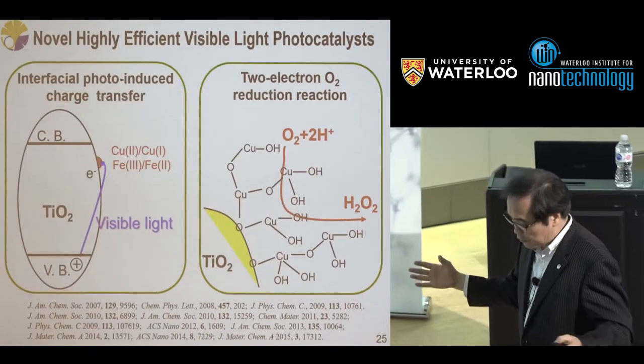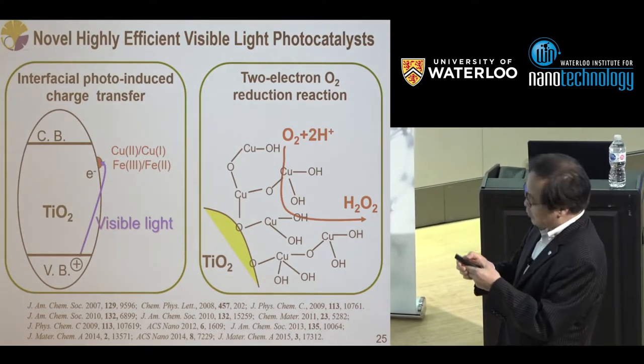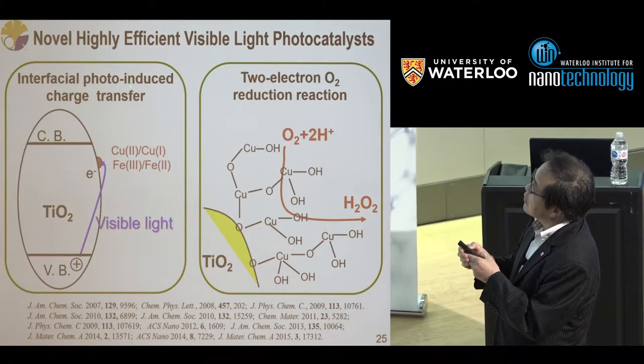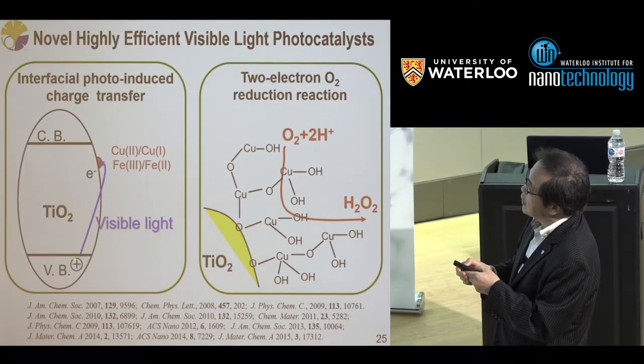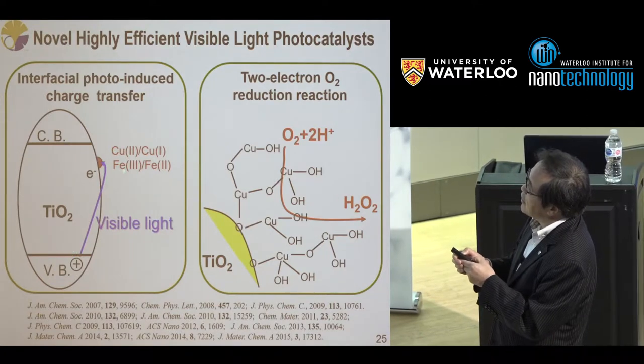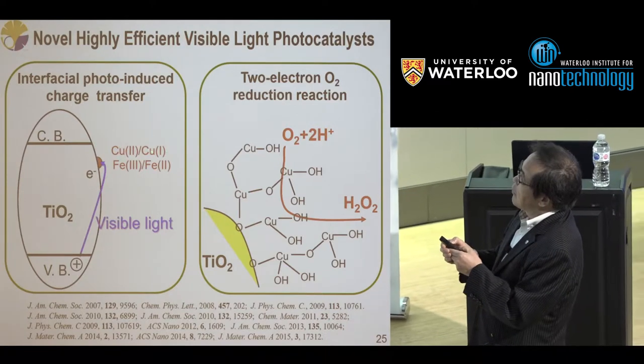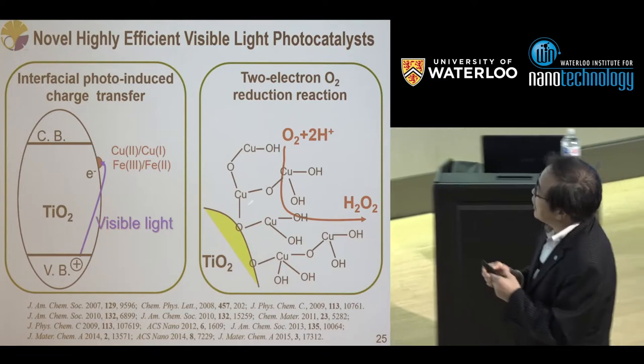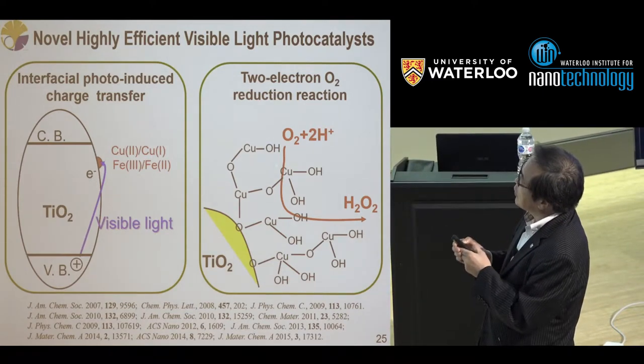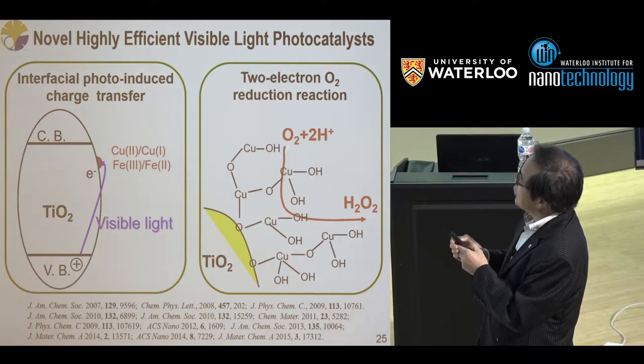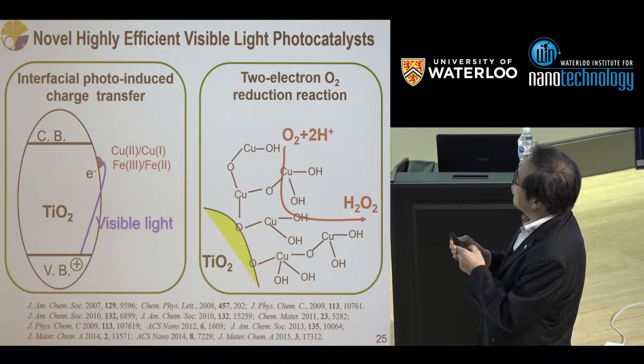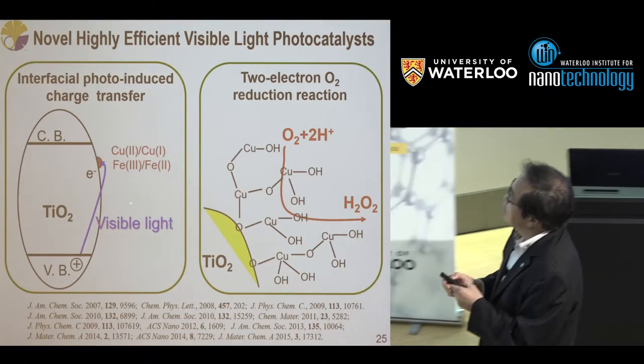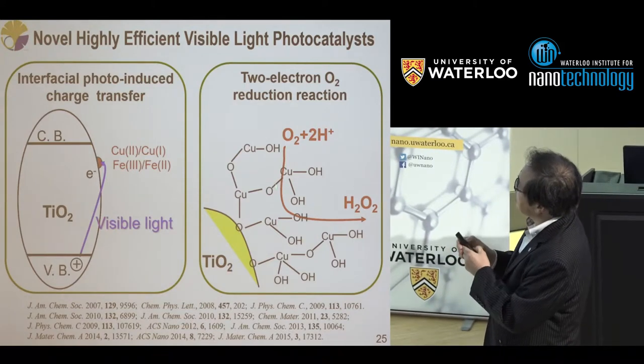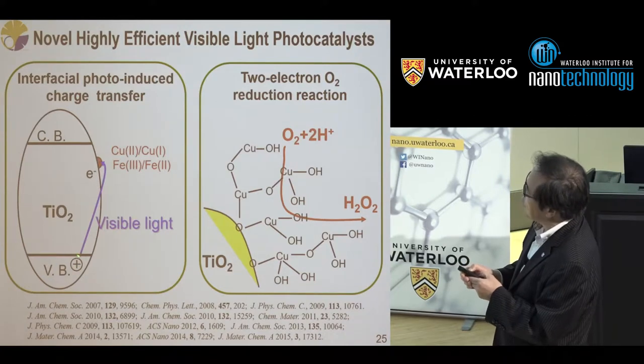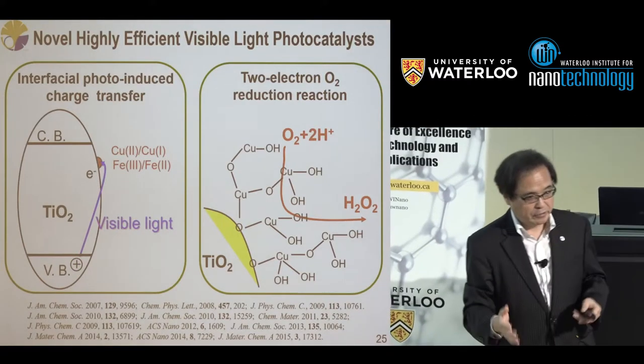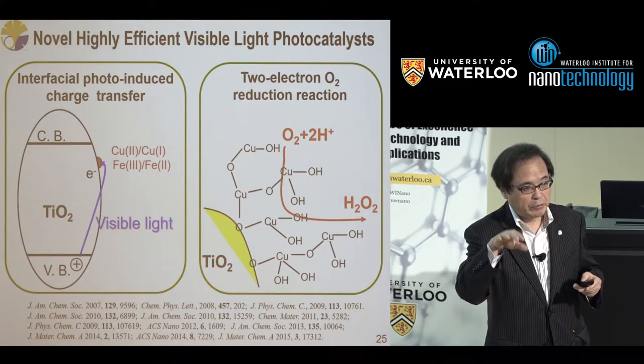What happens? To make the long story short, this new band is due to the interfacial charge transfer. The valence band electron is excited to the divalent copper or trivalent iron cluster, forming monovalent copper or divalent iron. And monovalent copper reacts with oxygen through a two-electron reaction, forming hydrogen peroxide. So this electron is consumed by the two-electron reaction, and the valence band holes with strong oxidation power remain. That's why it works under visible light illumination.